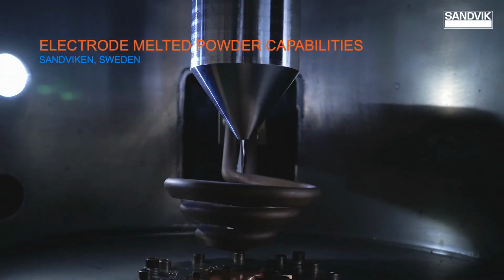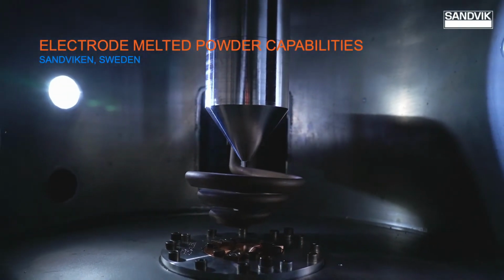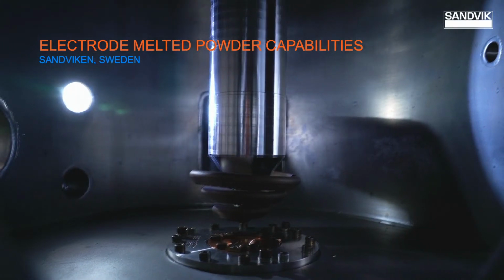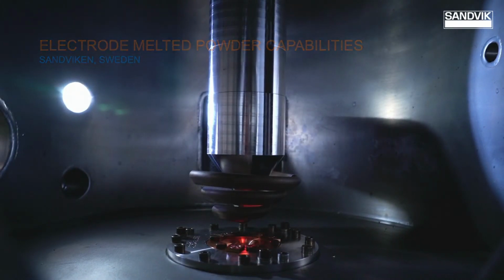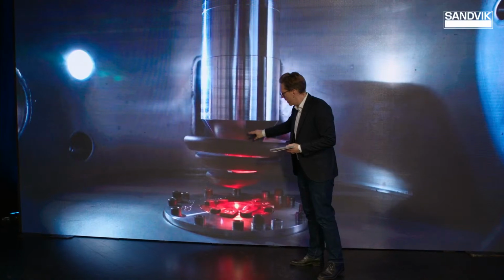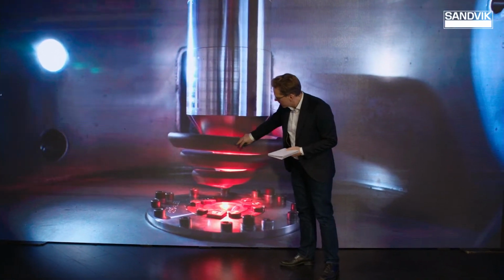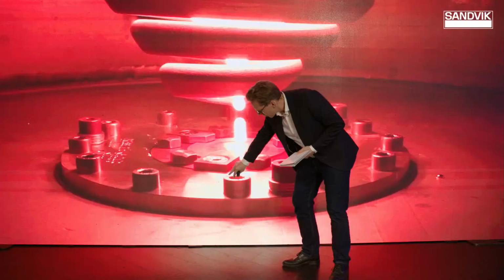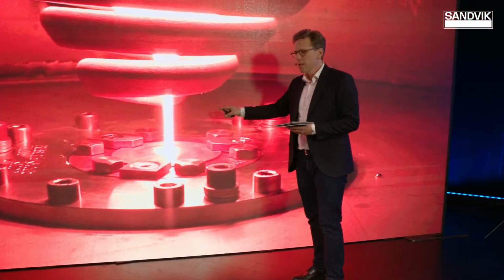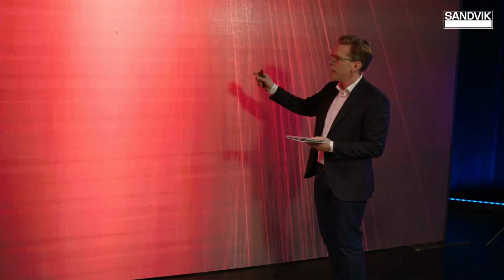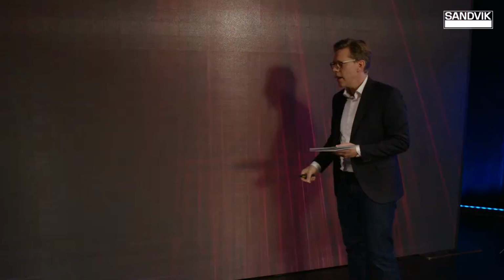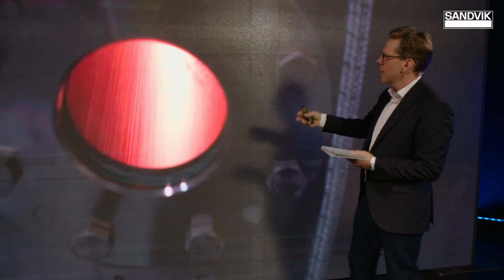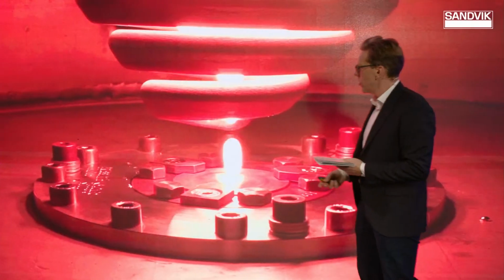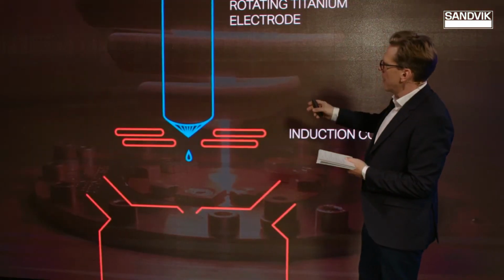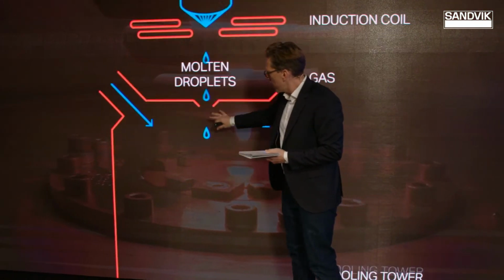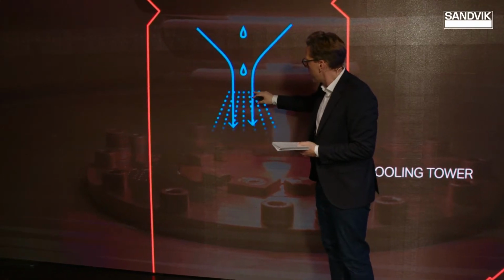This is a movie about it that shows that we use an electrode that we put down into an induction coil that is conical at the end. So we heat this part up and it starts to melt, and as you can see, droplets start to fall, and then a small melt stream is created, and a lot of things happen inside, and you get curious, what is this? And schematically said, when the droplets go down, it's more like a stream that is then